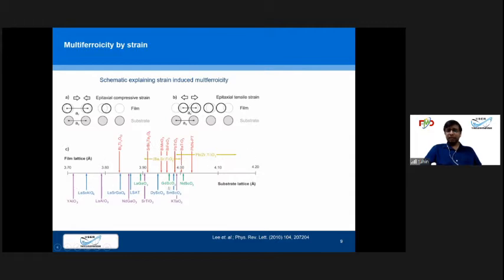Luckily, if you see that these are the substrate's lattice parameters and these are the material's lattice parameters, there are a number of substrates available which have a similar lattice parameter to the material we want to deposit. So if we choose one substrate, for example STO, and we choose this bismuth titanium oxide, then we can create one kind of strain. Or we can choose the BiMnO3, which can create another kind of strain. So by depositing epitaxial material onto different substrates, we can create a different kind of strain or pressure in the material.